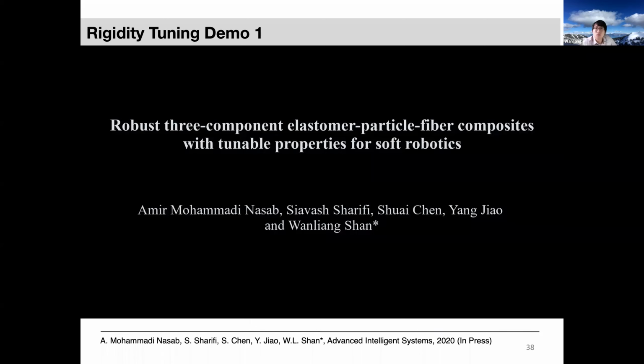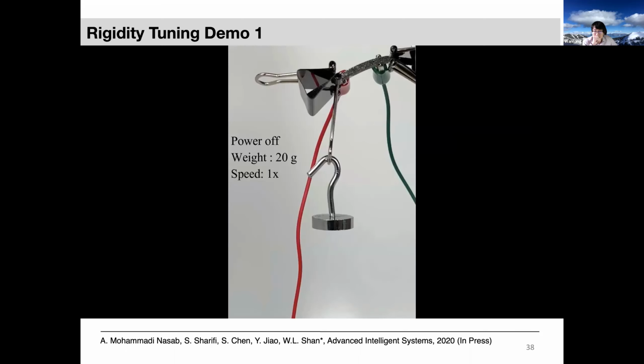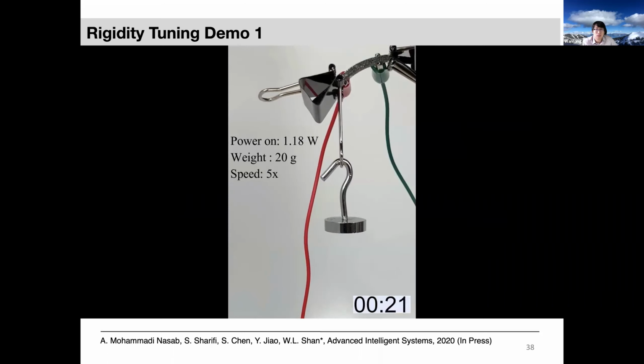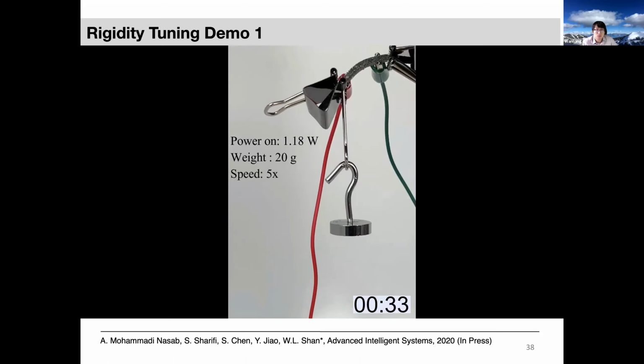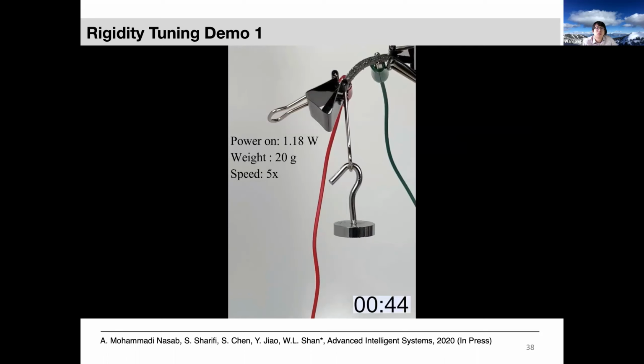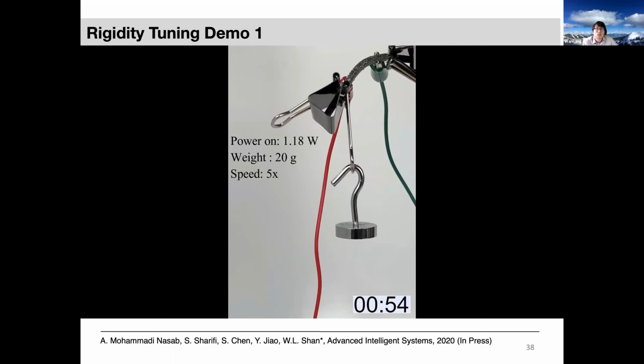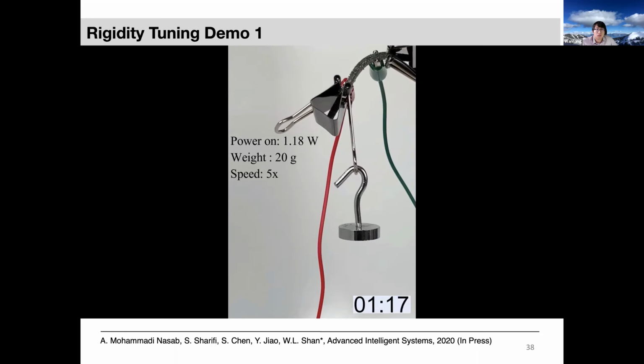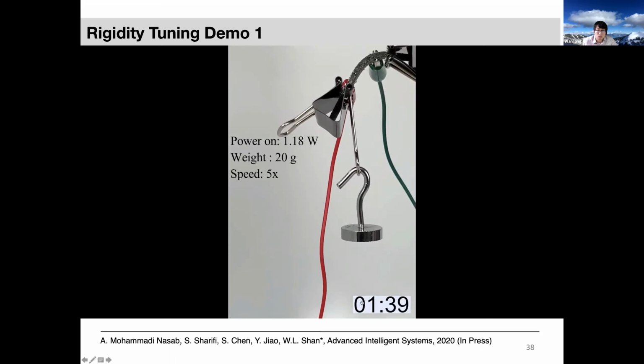Here's a quick demo of this material. In this case, we use a relatively low power rate. This was sped up 5 times. You can see after roughly 1 minute or so, we are able to soften this part.